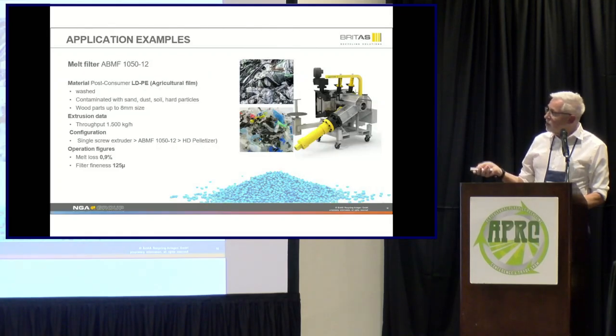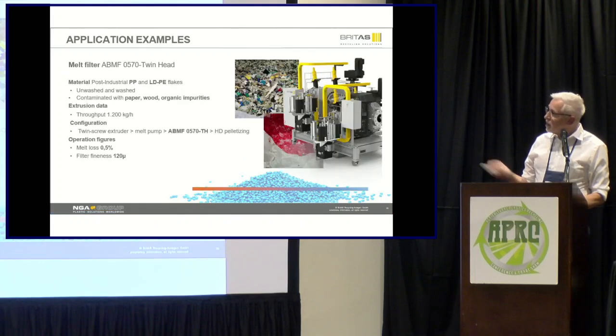Some examples, for example, a mid-sized standard filter in agricultural film business in combination with a single screw extruder and an HD pelletizer. Melt loss in that case is 0.9%. A smaller twin head in combination with a twin screw extruder, a melt pump, and HD pelletizing. Filter fineness 120 microns with melt loss of 0.5%.